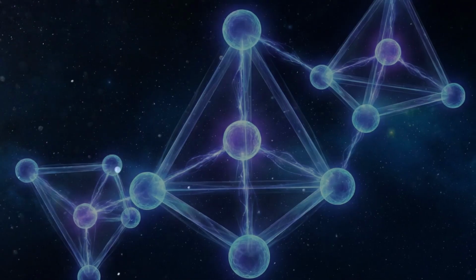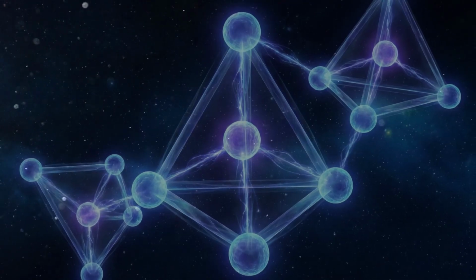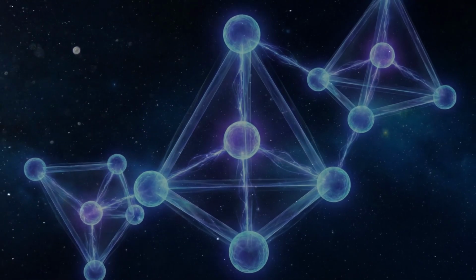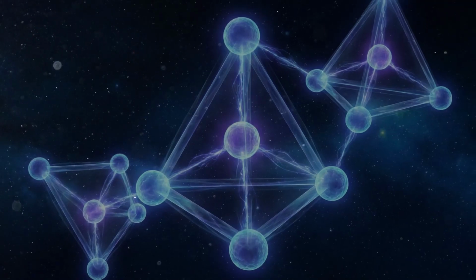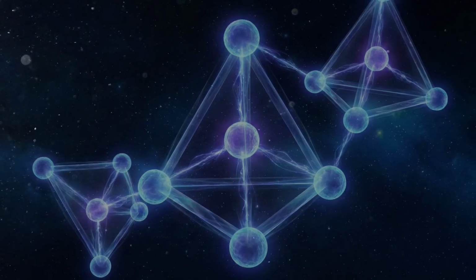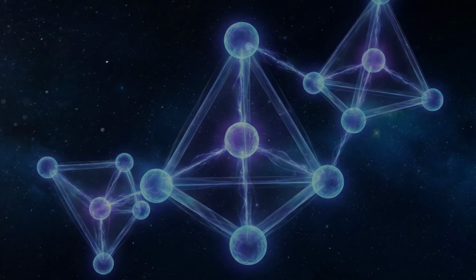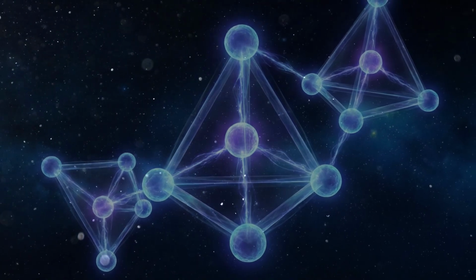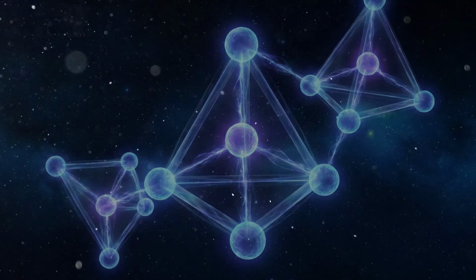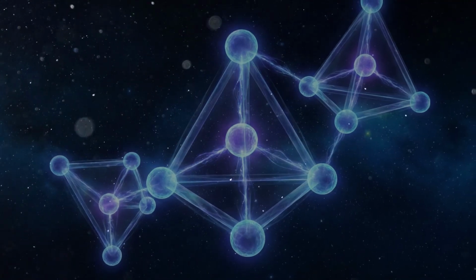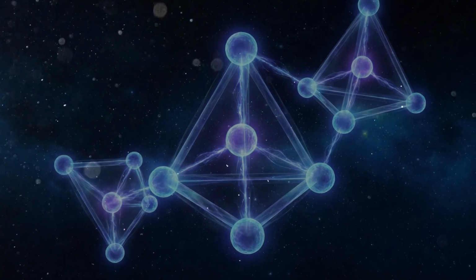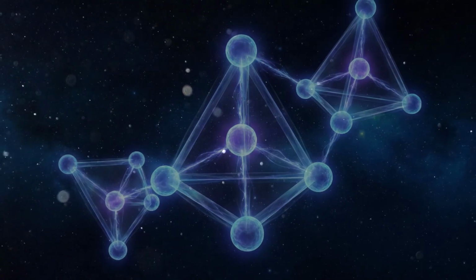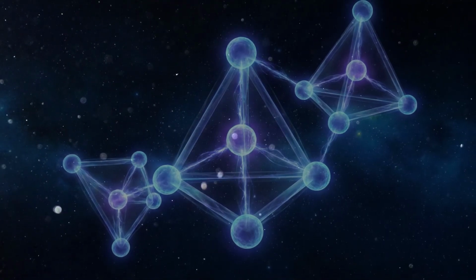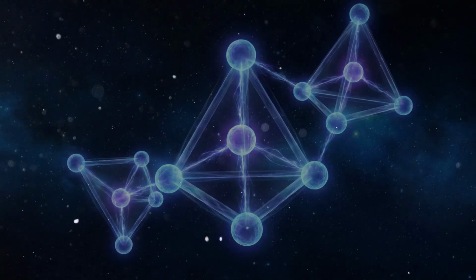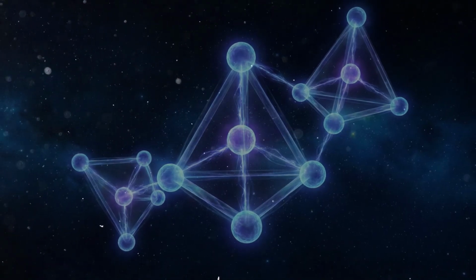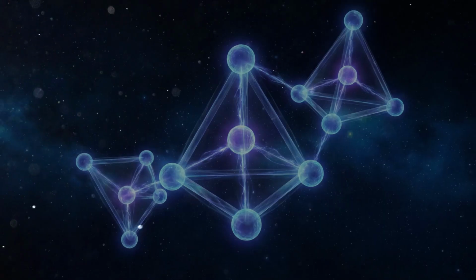This chirality, this handedness, is absolutely essential for the piezoelectric properties that make quartz so valuable in electronics. A centrosymmetric crystal, one with a center of symmetry, cannot be piezoelectric. The asymmetry of quartz's structure is precisely what allows mechanical pressure to separate positive and negative charges within the crystal, generating a voltage. Most natural quartz achieves remarkable purity.